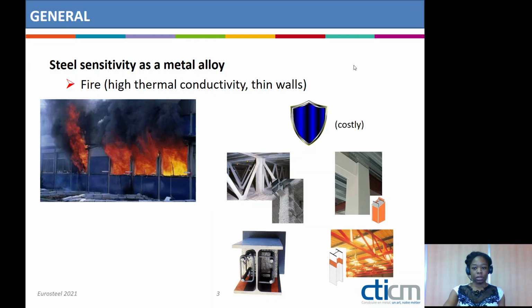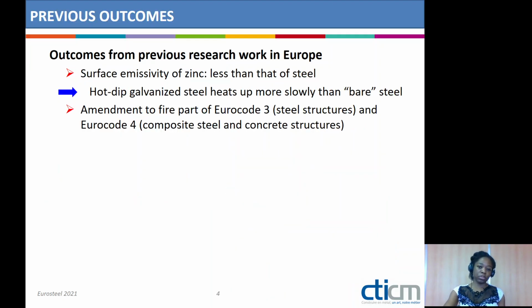Well, a few years back, some research work was carried out in different laboratories in Europe on the basis that the surface emissivity of zinc is less than that of steel. As you know, the higher the surface emissivity of a material, the higher the temperature that it can reach when exposed to a fire. So the main outcome of this research work was that hot dip galvanized steel members heat up more slowly than bare steel members.